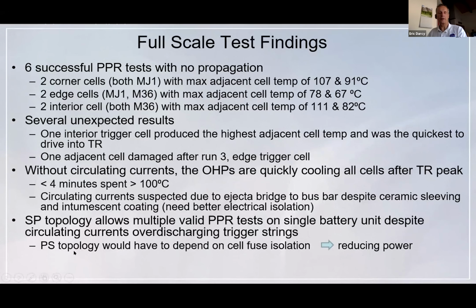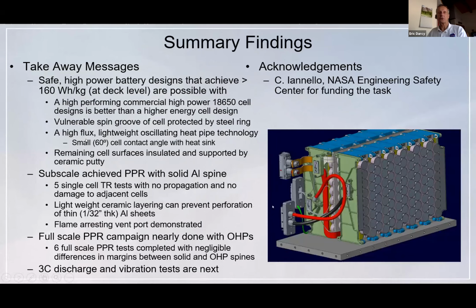If we had used a P before S topology, we would have had to use fuse isolation on every cell, and that would have added impedance to the pack and reduced the power of the pack. So the takeaway message is that it is possible to build these battery packs that achieve high energy and high power and be safe.